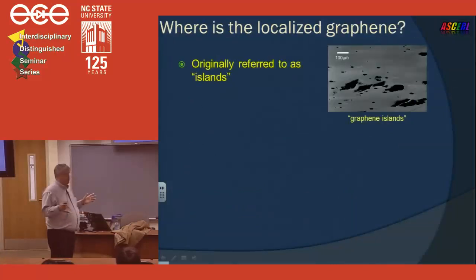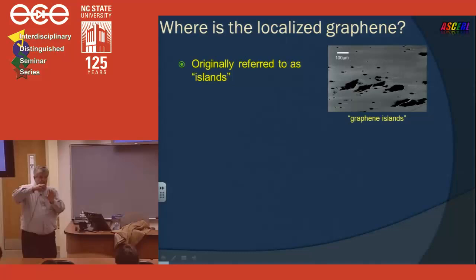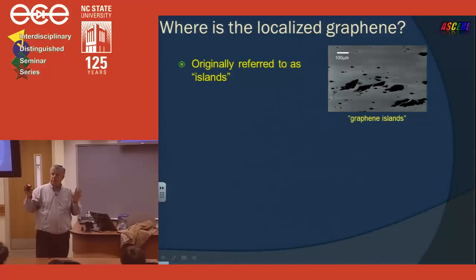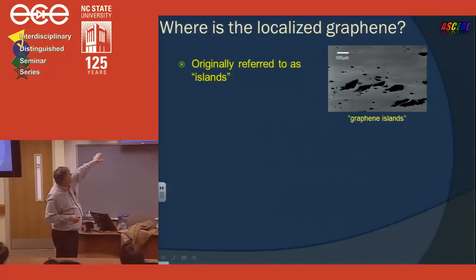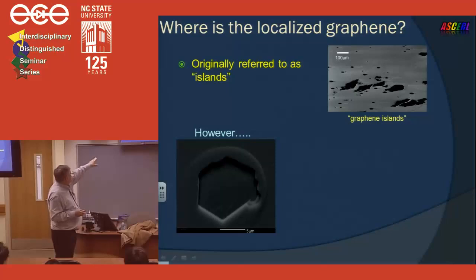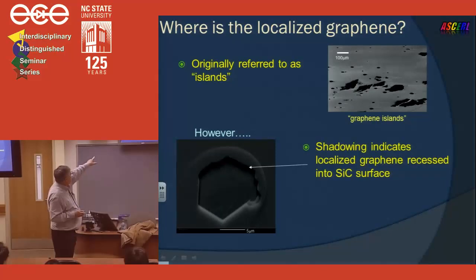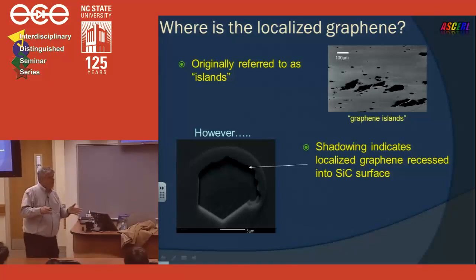So let me just walk through the rest of this. We now create the graphene under those conditions where we get the localized growth. So we just dial in the pressure and the temperature, and we get the localized growth, and that's what it looks like in a normal SEM. The little black areas are graphene. And notice some of them are larger, some of them are smaller, and they're scattered about in a somewhat chaotic fashion. We can zoom in on some of these features, and now we use ECCI, and you can see that where the graphene is, it's below the surface. And really, that makes complete sense, remember? Because graphene is a silicon sublimation process, so when I form graphene, it should be below the surface.